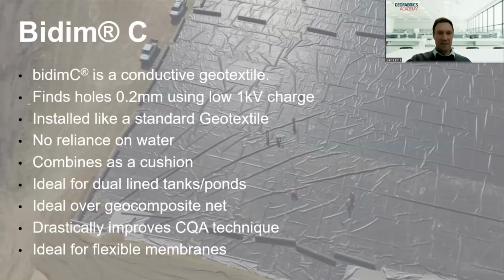Prevention of leaks, spark testing. I won't spend too much time on this, but there are options out there. You can do conductive backed HDPE. We've got a conductive geotextile, Bidim C. Effectively, you're placing this conductive medium below your primary liner, connecting a conductive broom on a cord, clipping it onto the edge of your geotextile, and then walking along your primary liner. And where there's a hole in the liner, you'll get a spark jump and complete the circuit onto your broom, and an alarm will go off and you'll effectively patch it.